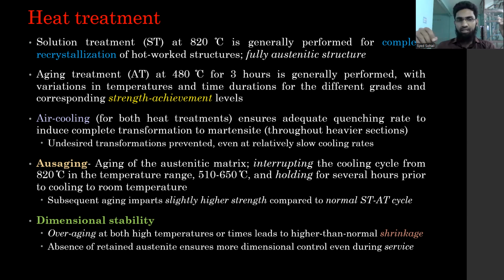Second point is that absence of retained austenite ensures more dimensional control even during service. Not just from the perspective of softening, but even from the perspective of service. In service also, retention of austenite comes off as an issue. So this is something repeatedly seen in the research papers, that they see how much austenite is retained. And we can start to have an understanding of why this is an issue, or is it an issue, and then why it is an issue. So dimensional stability requires or entails that austenite should not be retained, or should not be reverted. There should be no reversion of austenite.